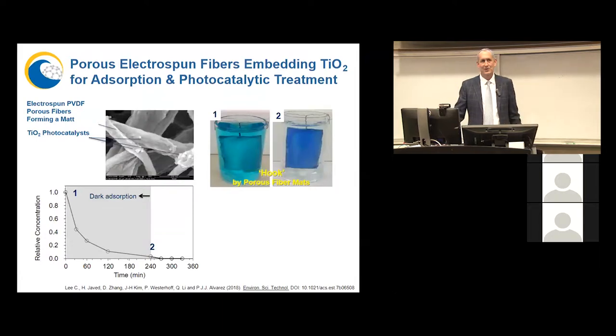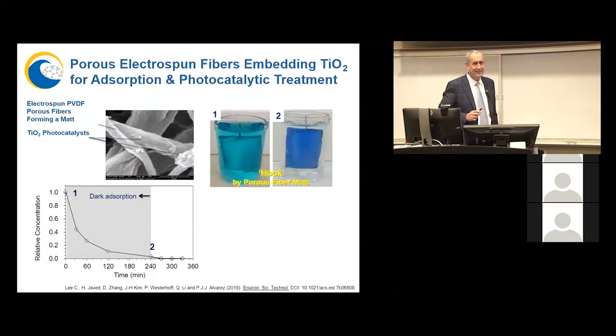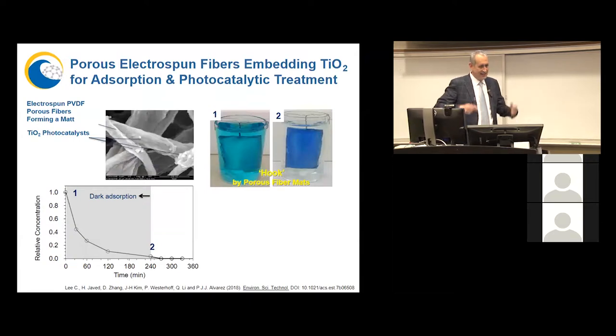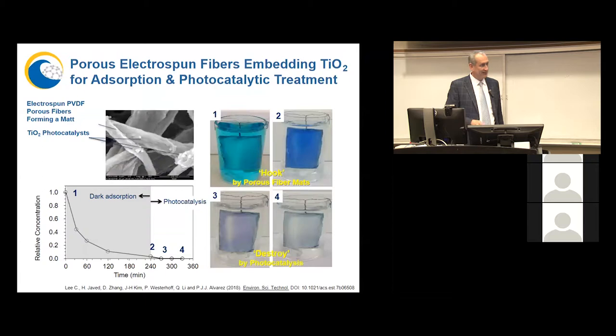So we're using, in this example, methylene blue because it's easy to visualize. And we're separating the two processes. First, the bait. As you can see, the polymer absorbs methylene blue, and now this water is treated. And we do this under dark conditions. And then we turn on the light to destroy the methylene blue and regenerate this photocatalytic mat.